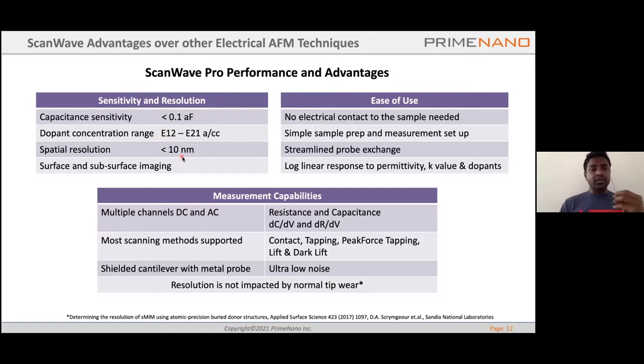All of this with a spatial resolution less than 10 nanometers. Again, this depends on the sample, but we have reached sub 2 nanometer spatial resolution as well. And we will talk about a couple of examples where we achieved that. As we are using microwaves, you're not only looking at the surface information or the surface response, but you can also look at the subsurface imaging as well.